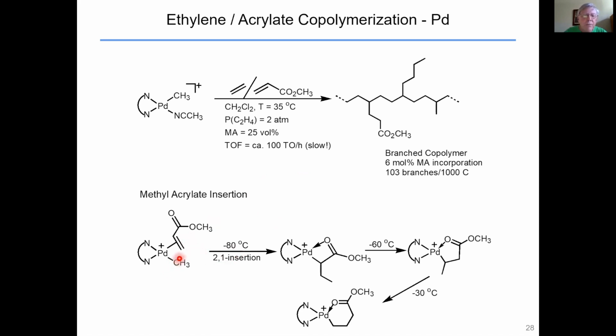It migrates to the beta carbon. This forms a 4-membered chelate. Palladium walks down the chain to make a 5-membered chelate, and then further to make a 6-membered chelate. And this is the catalyst resting state in the copolymerization of ethylene and methyl acrylate.